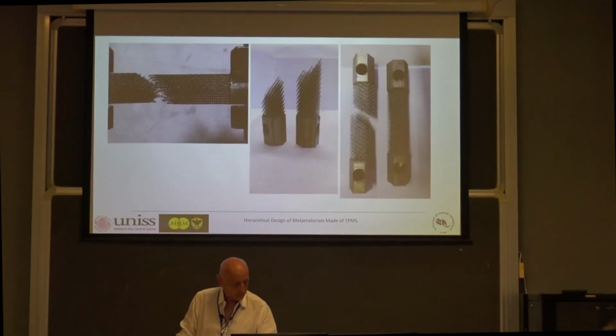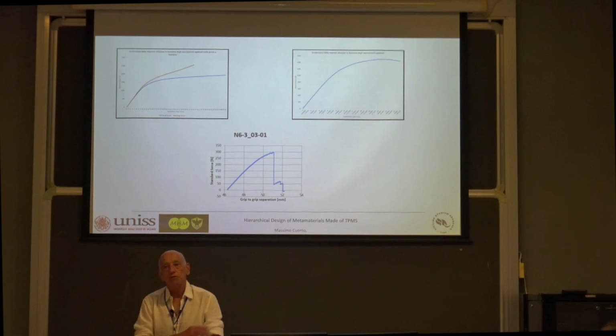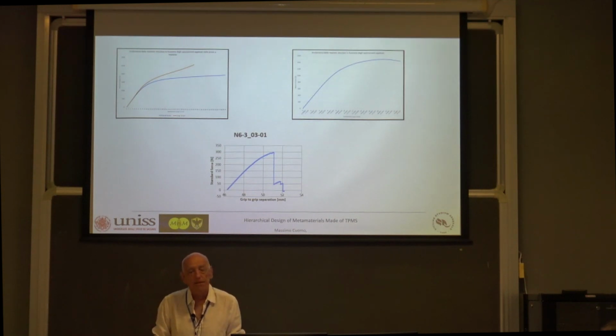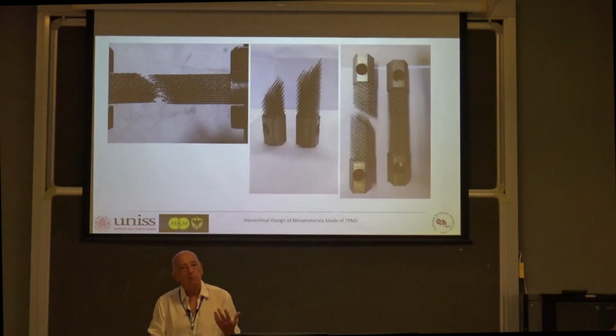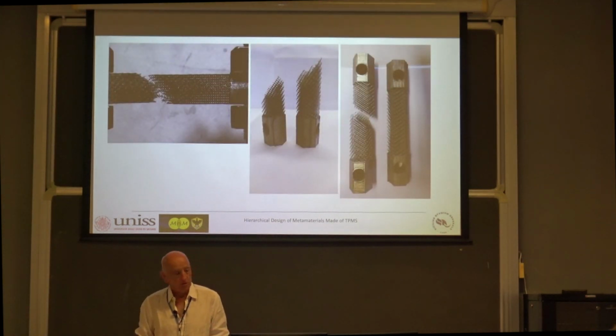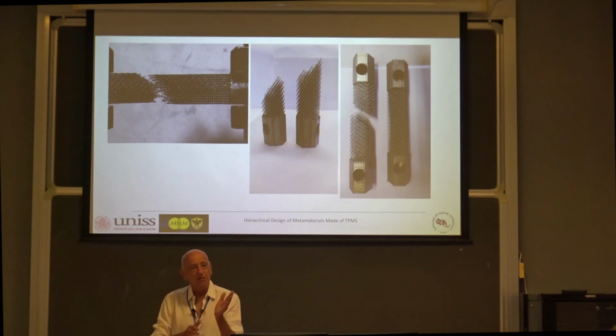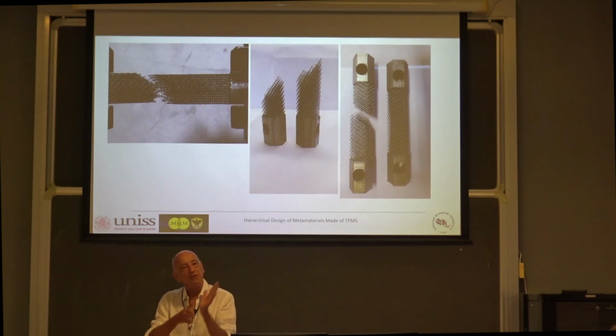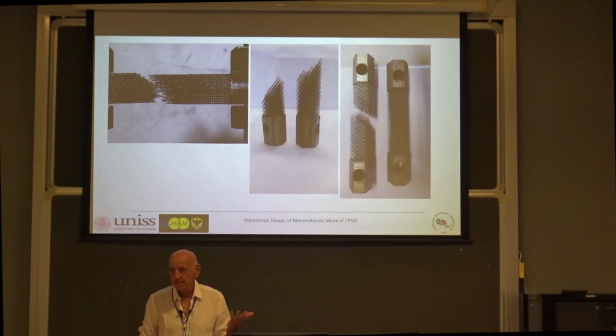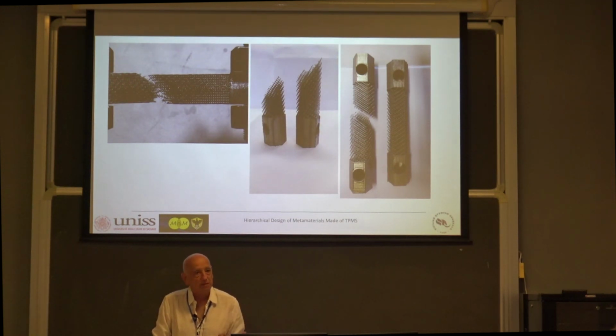On top is the analytical prediction we were expecting. On the bottom is the experiment. So completely different. And also the level we reached was much lower than the one we expected. The reason is that the sample behaved in a completely brittle way. It's very interesting because at first look you can see the bands, 45-degree bands, which seem like a ductile rupture, but the rupture of the single microbeam was totally brittle.